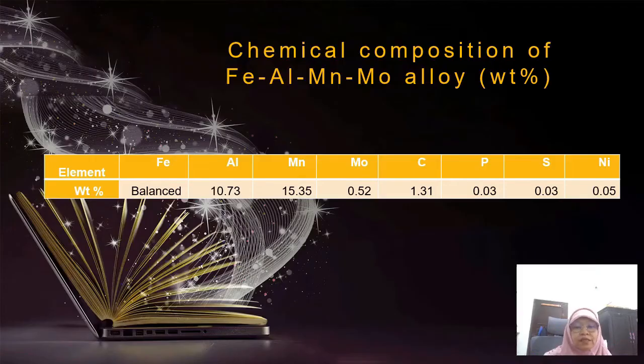In our research, the chemical composition of the Fe-Al-Mn-Mo alloy is Al 10.73%, manganese 15.35%, molybdenum 0.52%, and C 1.31%.